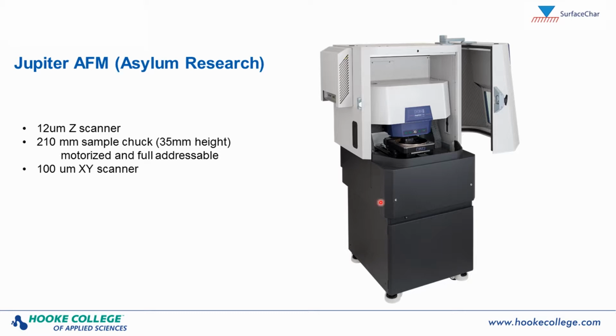And here are the pertinent specs of this new large sample instrument. In Z, it's got a 12 micron range, which is quite large. A lot of instruments usually only go up to 5 microns. Here's our large sample component, the chuck, this large circular portion here. It's a 210 millimeter sample chuck, and it can accommodate samples up to 35 millimeters in height, so a lot of flexibility there. The sample chuck is motorized and fully addressable. And the XY scanner is a classic 100 micron range in X and Y, classic for most of these large sample instruments.